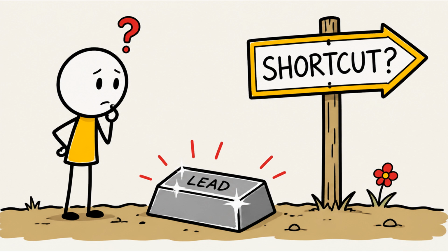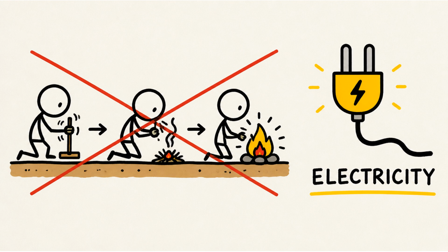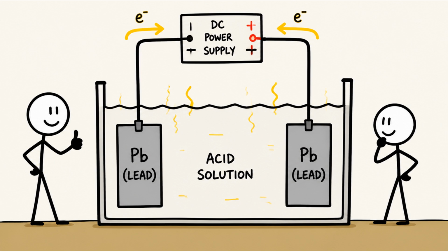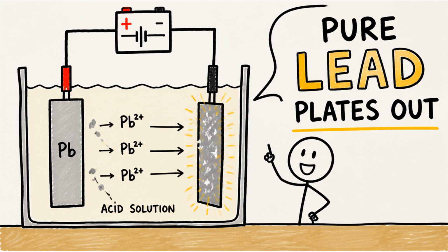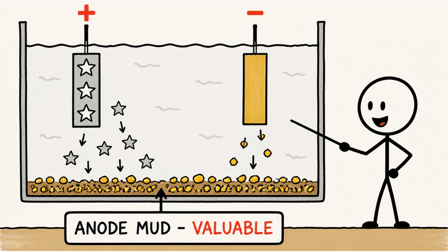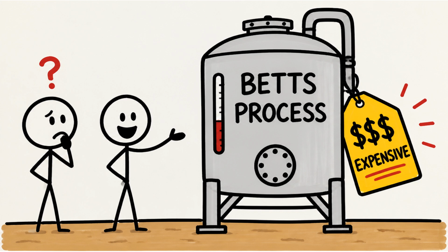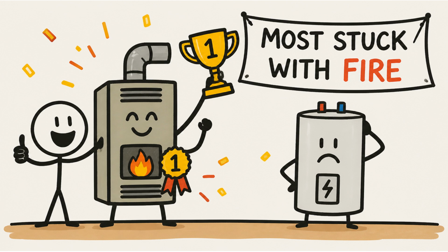Now, there is a shortcut. Instead of that whole fire refining sequence, you can purify lead with electricity. Cast the crude lead into slabs, hang them in an acid bath, run current through it, and watch pure lead migrate over and plate out clean, while the silver and gold and bismuth drop to the bottom as a valuable sludge. It's called the Betts process, and it's beautiful, but it's expensive, which is why most smelters, including the classic American ones, stuck with fire.